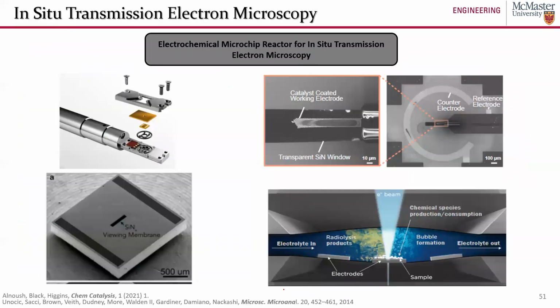Just diving into the details of what these microchip reactors may look like, it's essentially two chips on top of each other, sealed together, that we can flow electrolyte into. Within the chips, we have these silicon nitride viewing windows, and silicon nitride is essentially X-ray or electron transparent. So we can just fire electrons or X-rays through that silicon nitride window and illuminate our working electrode where our catalysts or our active materials are developed.